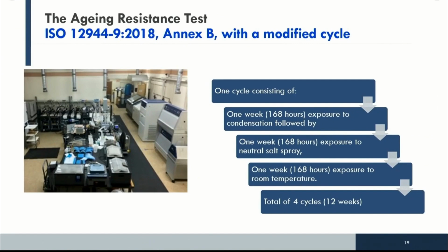We want to age the sample. We conducted it according to ISO 12944-9. However, we modified it in order to simulate conditions in the field. So we did 4 cycles. The first cycle was 1 week exposure to condensation, followed by 1 week exposure to salt fog, followed by 1 week of dry condition at room temperature. And after each cycle, we took samples and evaluated the performance of the coating.